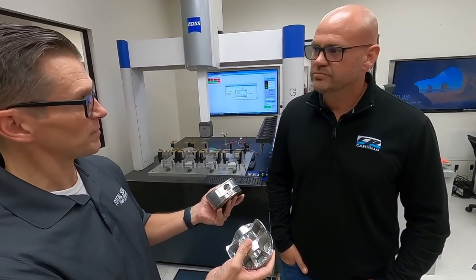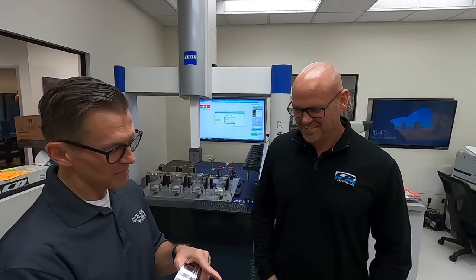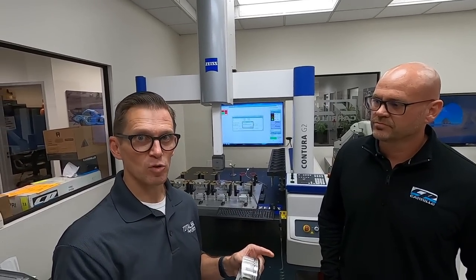The biggest thing we did is essentially the same bore size, but going from 4.060 to 4.065 just to clean it up — and we had rings available for that. We went from a 0.043, 1.5mm, 3mm ring package to a 0.7mm, 0.7mm, 2mm ring package — quite different. This old one was a ductile Dynaforged top ring, and the new one will have a steel PVD-coated top ring. What's PVD mean? Physical vapor deposition.